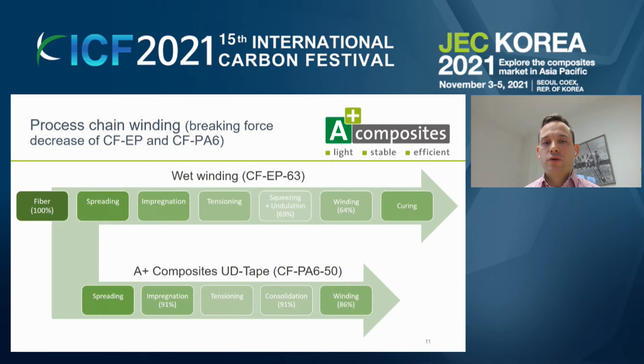If you now go the thermoplastic route, like my speaker before, you can find out that even 91% of the breaking force is still remaining in the tape, which is quite a lot. There are some differences between the fibers and the linear densities of the material, but the magnitude is quite the same. And if you now do the laser welding with different lasers, or what we have done, for example, with the hot gas torch, you can maintain most of the strengths. If you now wind it up again, you have some effects because of the inner and outer surface length. So you can achieve about 86% of fiber strength, which is quite a lot, but I think there's still room for improvement to get a better fiber spreading and a better fiber tension.